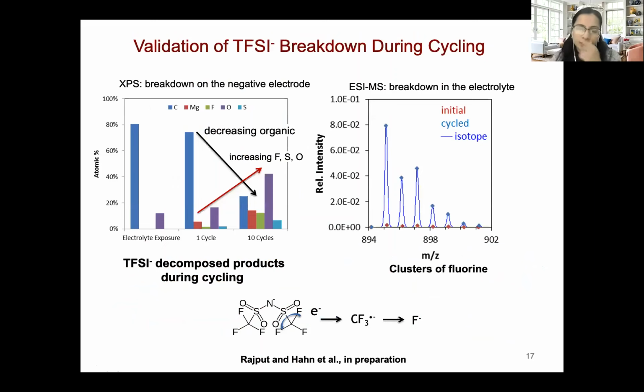And our experimental collaborators at Sandia National Lab were able to validate this TFSI breakdown mechanism, where they found some TFSI decomposed product on the electrode during cycling, which is an indication that TFSI is breaking down. And they also observed some fluorine cluster in the solution, which shows that we are breaking this carbon-sulfur bond and liberating fluorine in the solution, as was predicted by simulations.